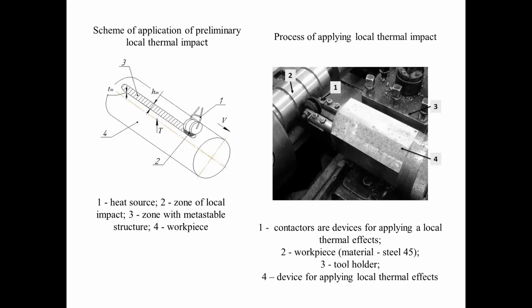When thermal radiation interacts with the surface layer of the part along a straight trajectory T formed by moving a heat source at the speed of V, which heats the surface of the part over 720 degrees Celsius, a localized metastable structure is formed with geometric parameters Tm, Hm in the assumed area of the removed allowance.